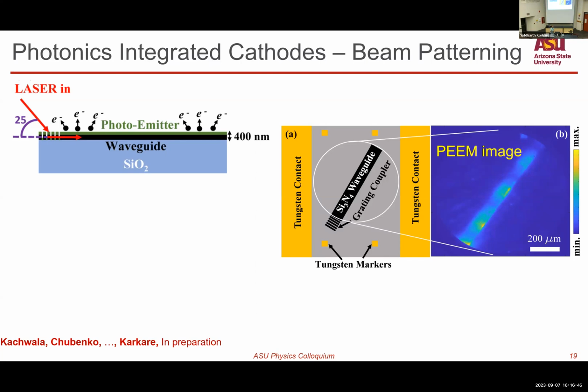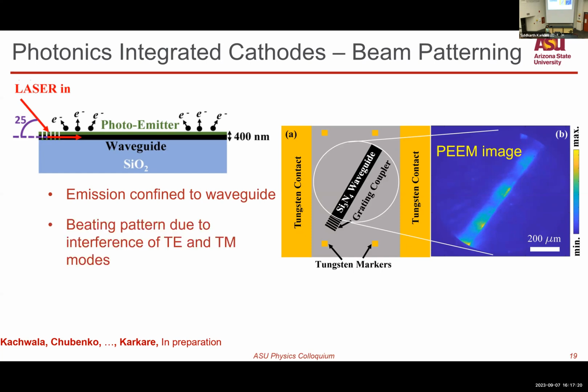And here, for the first demonstration, we have used a millimeter size waveguide and about 100 microns in the other direction, but we can very easily scale it down to a micron or even a sub-micron regime, and it should still be valid. It would be the first way of patterning the electron beam to sub-micron length scales. So we have shown emission confined to this waveguide. Further, we also see this very interesting beating pattern at several hundred micron length scales. And it turns out this beating pattern arises because of the interference of the transverse electric and transverse magnetic modes of light coupled into this waveguide.